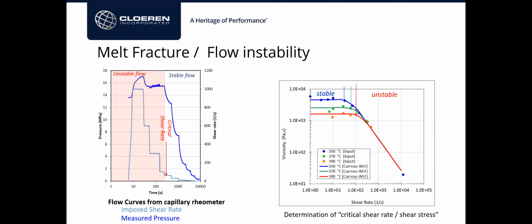Next, is there something in the polymer design, for example, molecular weight distribution, viscoelastic behavior, branching, additives, that could help avoid the phenomenon of die buildup in a BOPP process? Well, I have to look at the BOPP process. The skin layers are usually a little bit lower MFR than the core layers, but they're still in the 7 to 8 range.